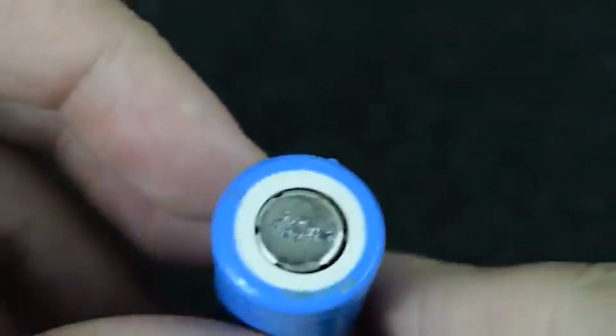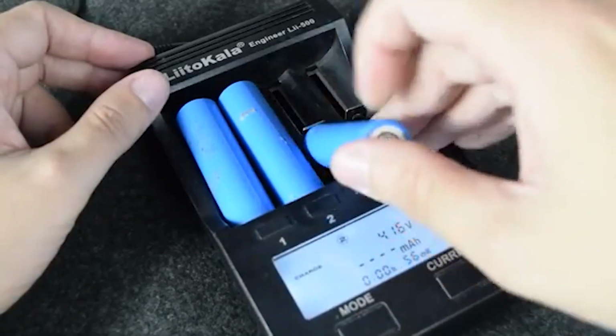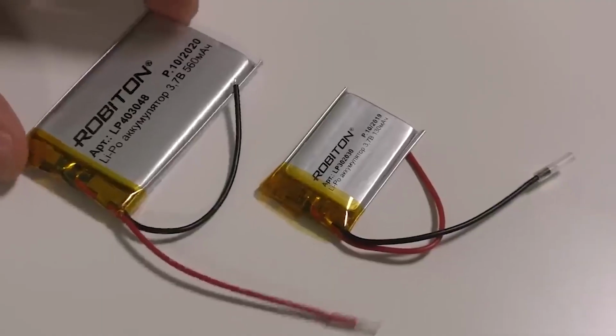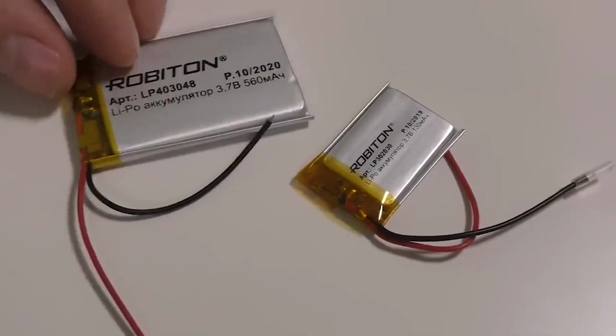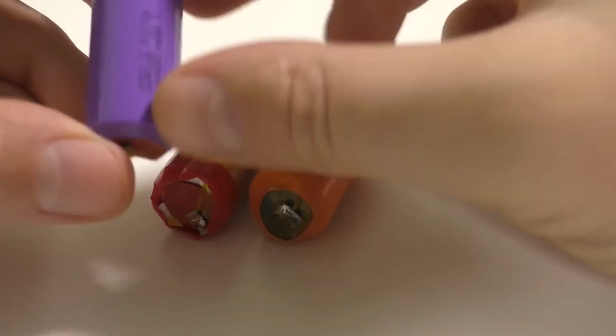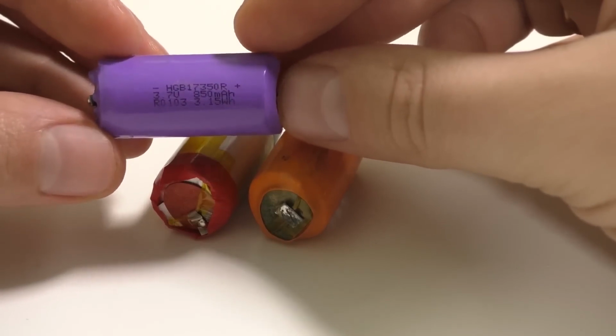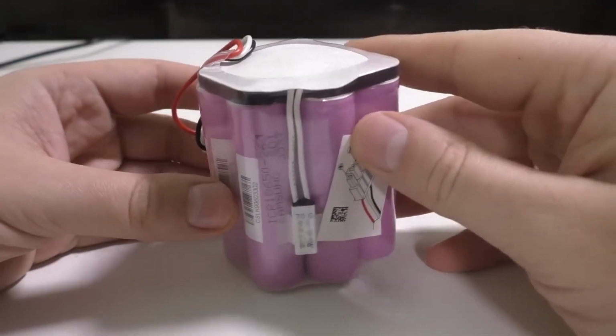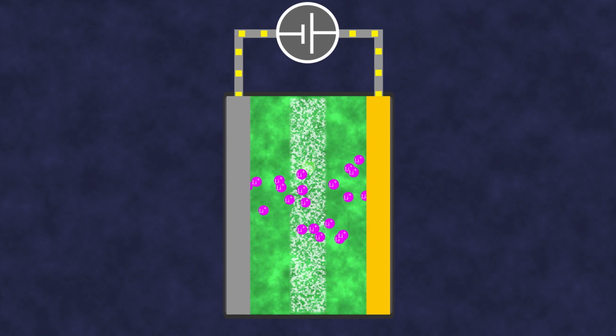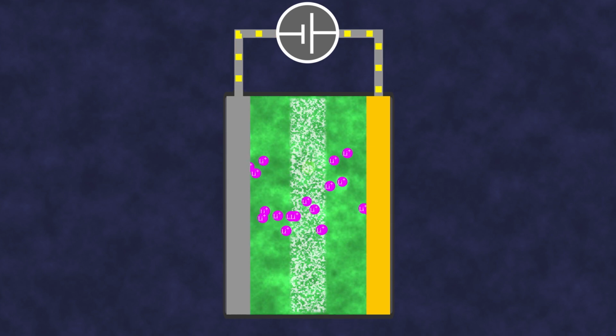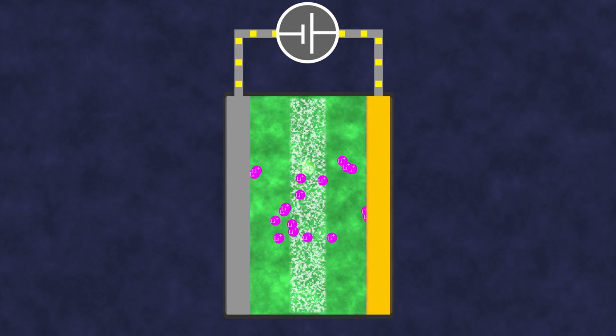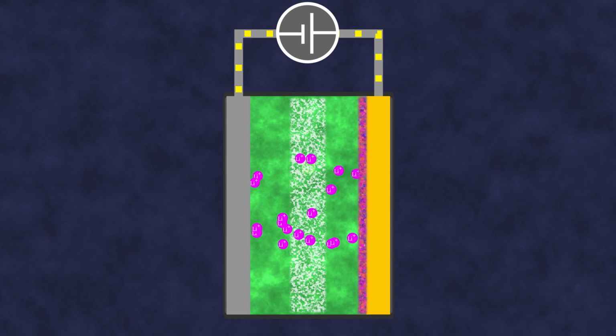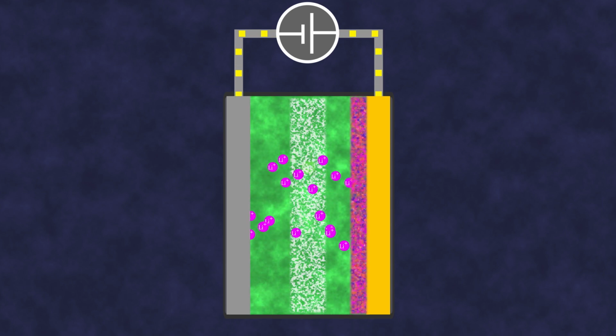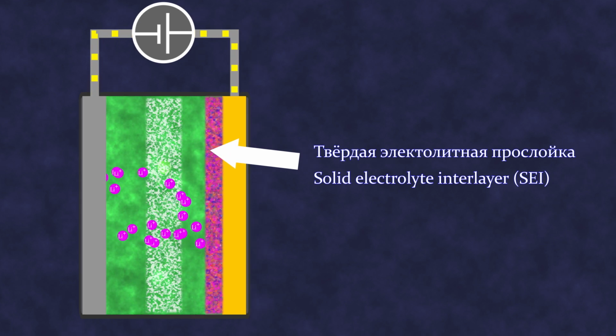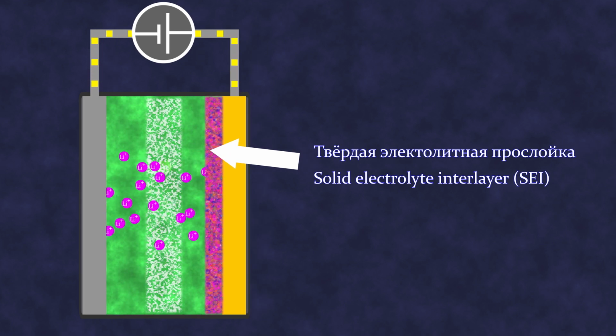The first lithium-ion batteries were recommended to be fully charged and then fully discharged as quickly as possible, repeating several charge-discharge cycles, which was supposed to significantly extend their lifespan and efficiency. Interestingly, this effect was not anticipated by the developers and was discovered during battery operation, and only later received an explanation. It turns out that during the charging process, chemical reactions involving the graphite anode, lithium, and various electrolyte components occur near the graphite anode, leading to the formation of compounds insoluble in the electrolyte, which form something like a protective barrier on the anode, the so-called solid electrolyte interlayer, SEI.